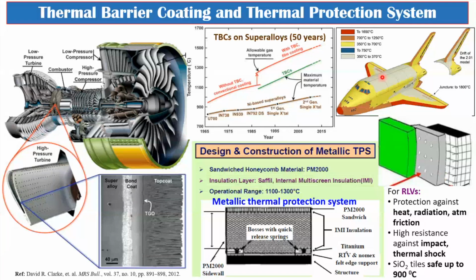So the first example I want to draw your attention to is this marvel called jet engines, aeroturbine engines. You have this large compressor region and combustion region. And in this combustion region, you have the blades which experience a temperature in excess of 1000 degrees. And that's where you need to prevent many other threats, one of them being oxidation. Typically this oxidation is prevented by way of a coating, which is a ceramic coating on the surface. But these thermally grown oxides form at the bond coat, which is metallic, between the bond coat and the top coat, which is ceramic. So prevention of this growth of the oxide layer is a very important exercise, and typically this is done by way of such oxide coating.